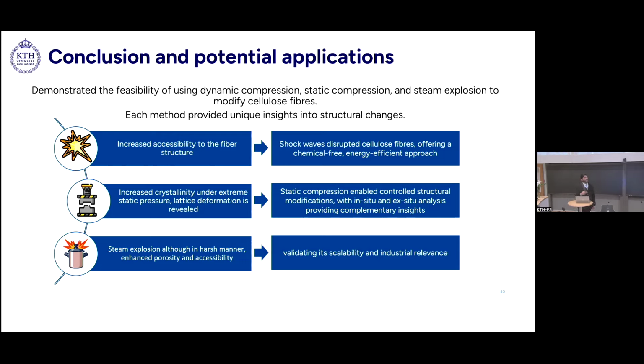And this could be a chemical-free process, and it can be converted into an industrially scalable process. The second project was more of an exploratory project, where we tried to establish higher crystallinity after application of gigapascal levels of pressure. We could also see how the lattice is getting deformed, and we could mathematically fit a curve through it to understand it for high pressure processing in the future. There was also a steam explosion project, which, although a very harsh treatment in terms of temperature, was still a good treatment in general to form nanofibrils at lower quality. And it's already an industrially scalable process, so it's one of the good processes to work with.